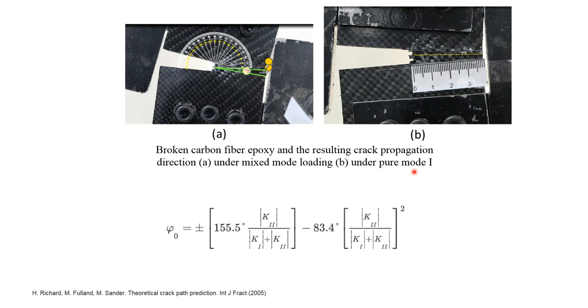The crack growth angle or crack propagation angle is calculated and shown here for 0 degree on the right, and for the 15 degree loading angle on the left side. For 0 degree it's 0, as you can see, and for 15 degree the angle is almost equal to 7 degree. The crack propagation direction can be determined theoretically using this relation proposed by Richard.